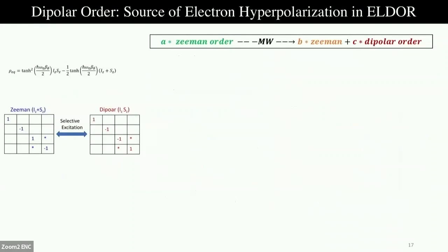From simple analysis based on product operators, we associate these hyperpolarizations or humps to be coming out of dipolar order. So if we look at the density matrix of Zeeman order and dipolar order, we can interconvert Zeeman order and dipolar order by selectively flipping a spin manifold. For example, if you flip this manifold, we go from Zeeman order to dipolar order.